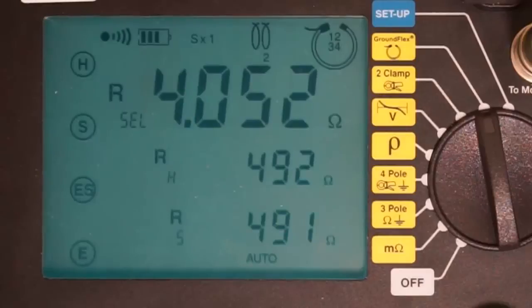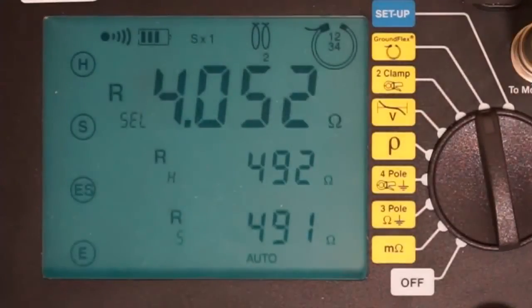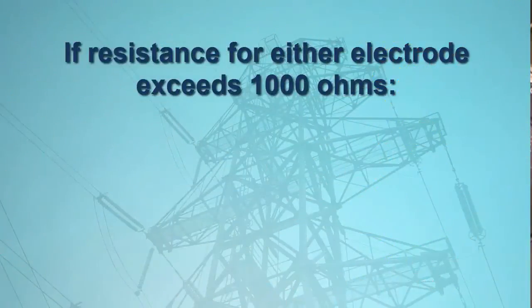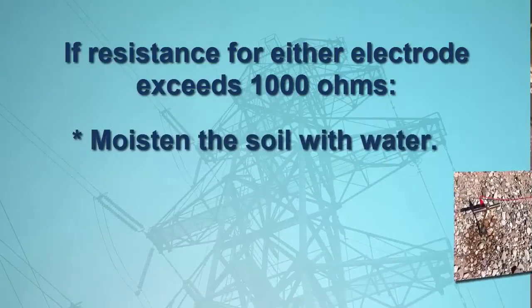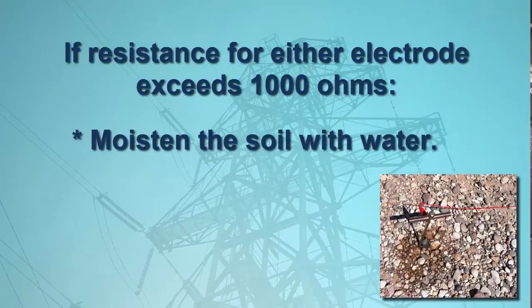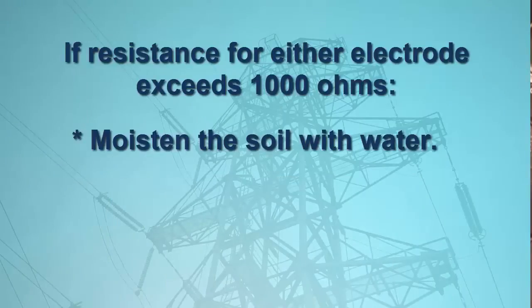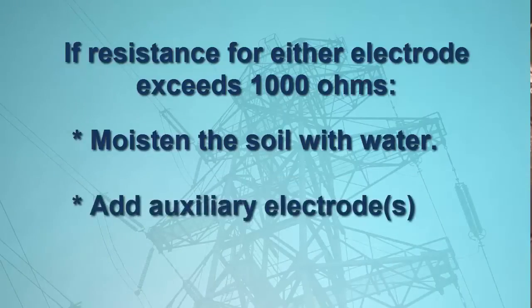This is because resistance determines the test current, and too low a current makes obtaining reliable results difficult. In this situation, an indicator consisting of greater than and less than symbols may flash, informing you that the measurement may be unreliable. If the resistance for either electrode exceeds 1000 ohms, you can moisten the soil around the electrode by pouring water on it, and then retesting. You can also connect additional auxiliary electrodes to each test electrode. These auxiliary electrodes should be placed in parallel with the primary electrodes at a distance of approximately 2 to 4 times the depth of the primary electrodes.